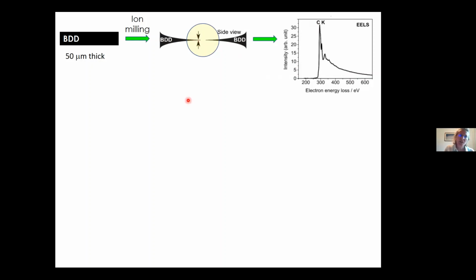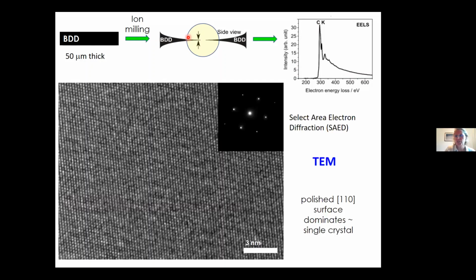So I said to you that we can get regions thin enough to become a TEM support. And when you look at it, the way our diamond grows is it's actually preferentially oriented with a 110 interface. And so when you do this selected area electron diffraction onto that BDD, you can see this beautiful single crystal of 110 surface. And so this is our support structure.